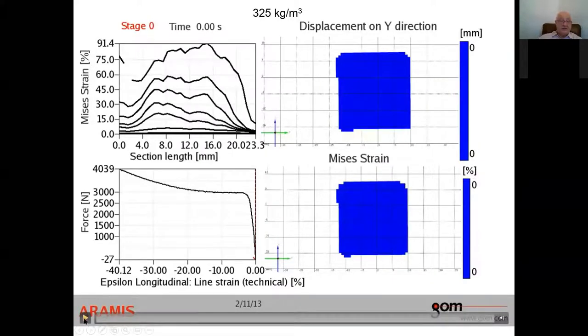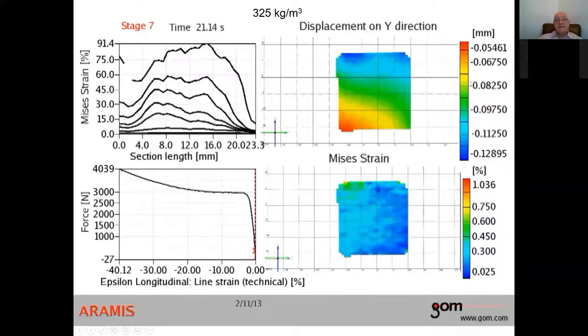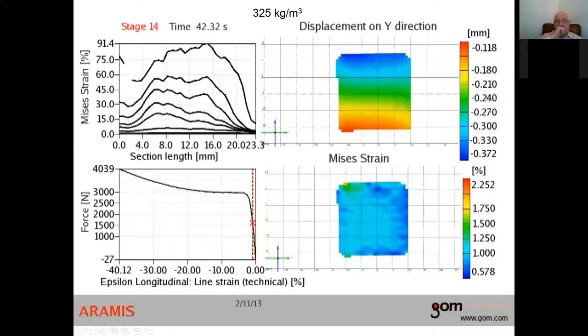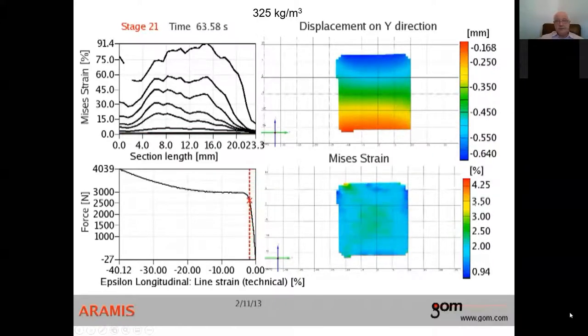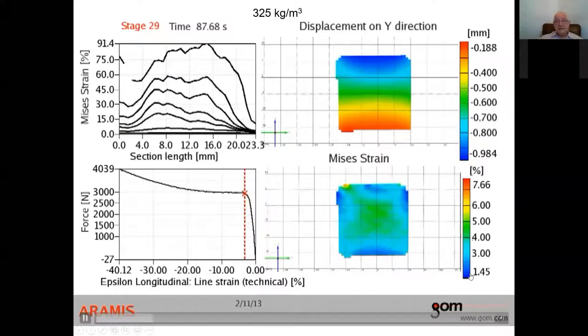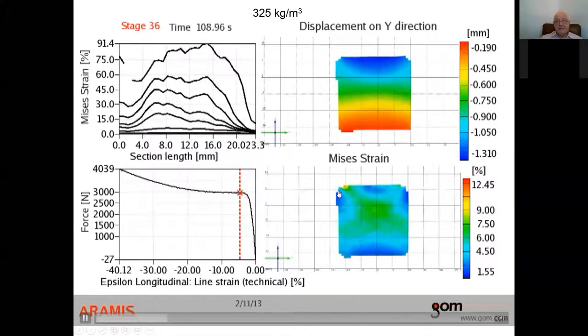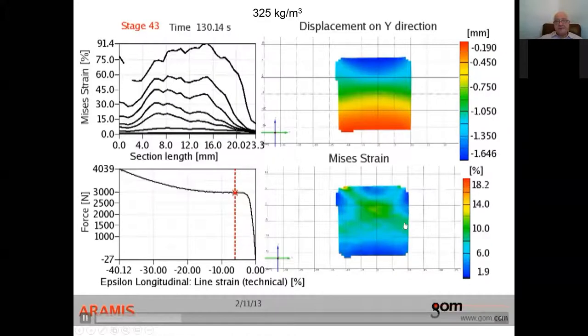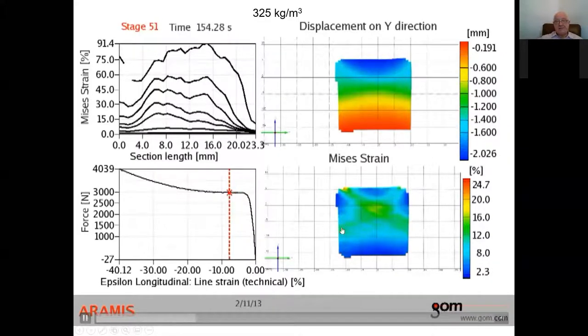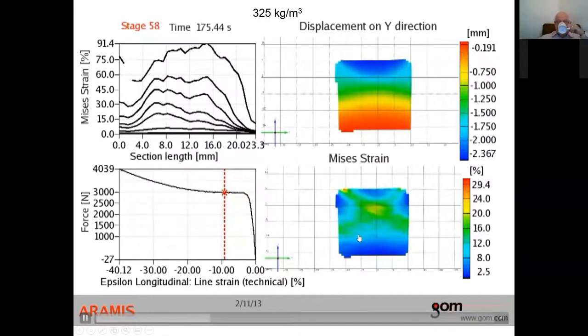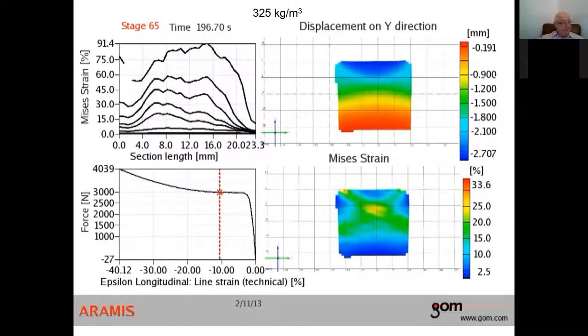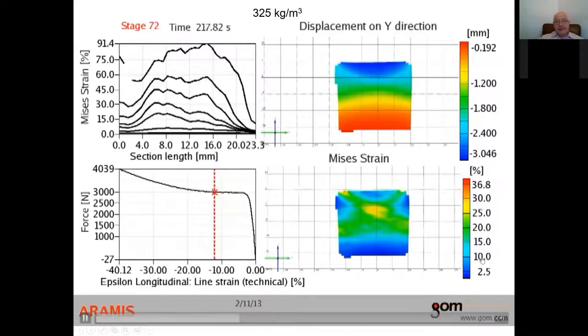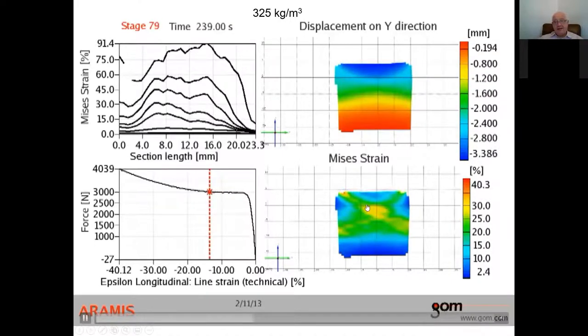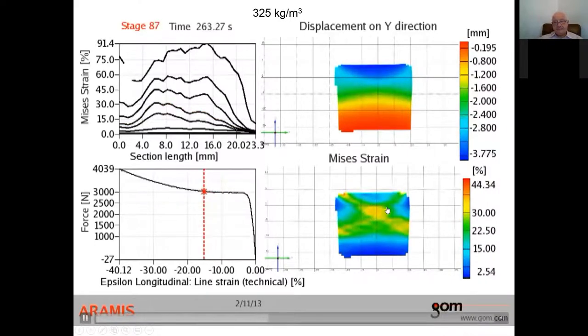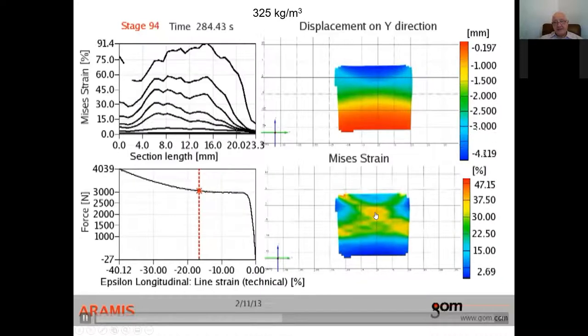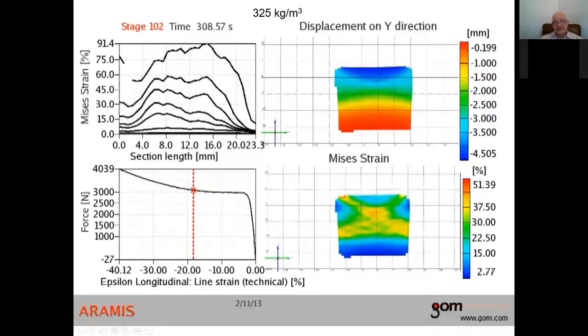Okay, and now 325, one more example, in which you have this X type of deformation bands, as I was mentioning before. And then this strain is localized at this intersection, and it's moving little by little.